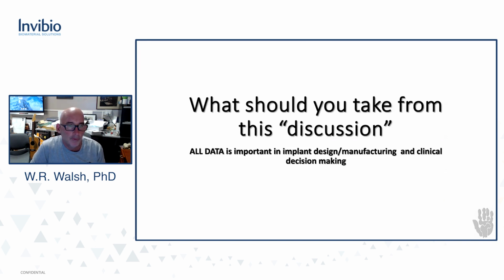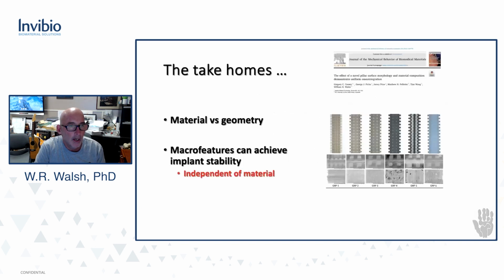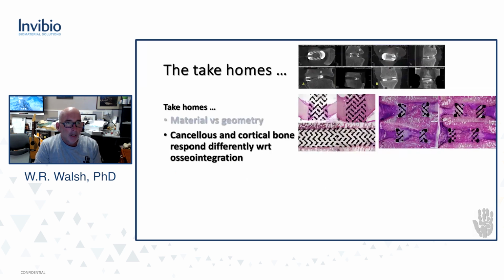I think all data is important at every stage of it, be it at the beginning, the middle, the end, and now the human clinical correlates, and really material versus geometry. I think it's important to realize that the macro features can often achieve stability independent of the material. We've shown that in this study with Greg. We showed it in the study with interbody fusion as well. Where you put the bone or implant has a big factor on what the bony response is. So don't assume that just because it grows in cortical bone, it's going to grow in cancellous bone or growing into a spine.